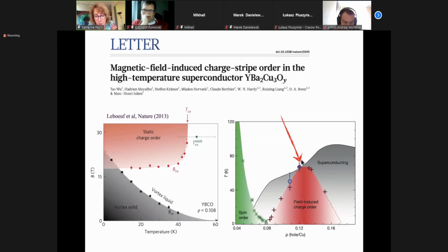And as I told you before, it's very typical of these high TC superconductors that the maximum value of the charge order, you can see it here as well, is of the same order of magnitude as the superconducting order parameter. So there are people believing that charge order is an epiphenomenon, but still, if it's an epiphenomenon, then why is the transition temperature of the same order as the superconducting temperature here?